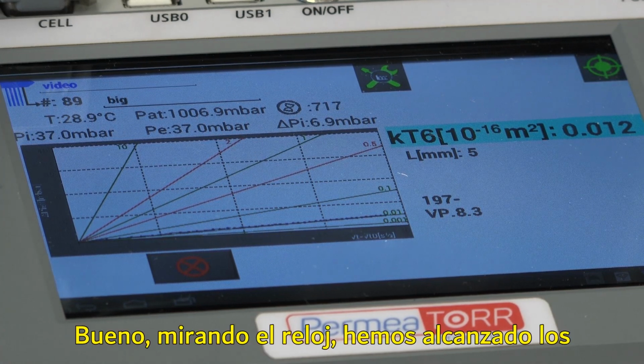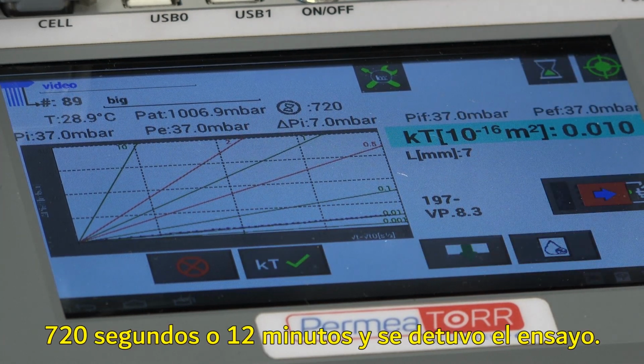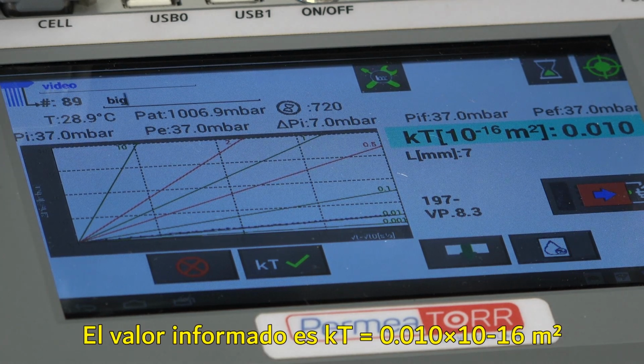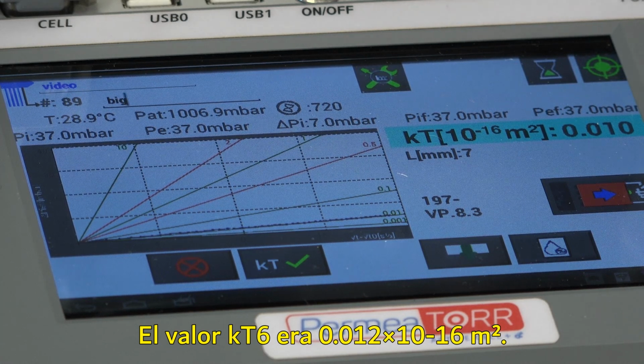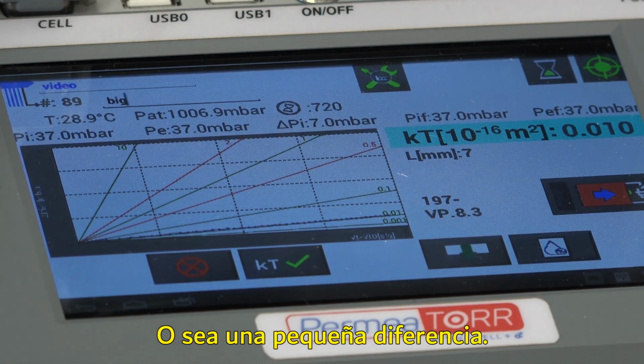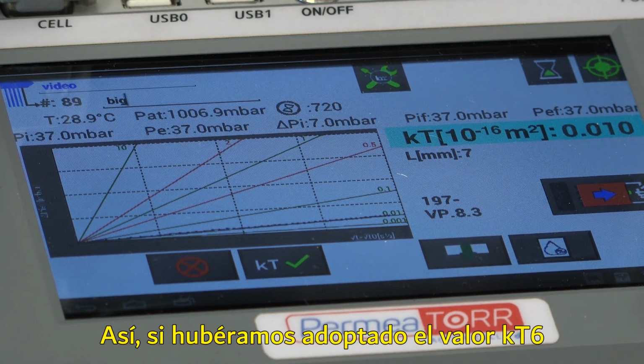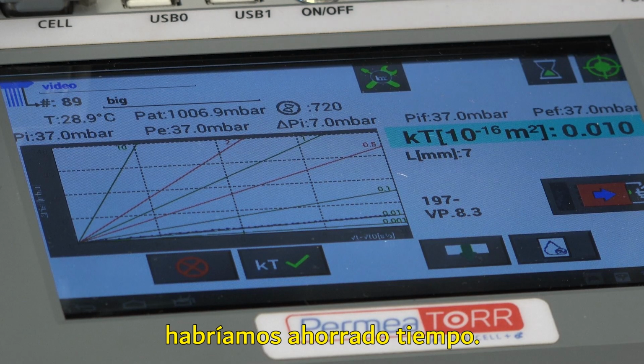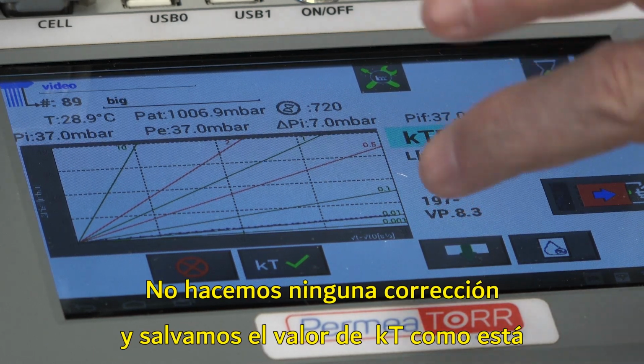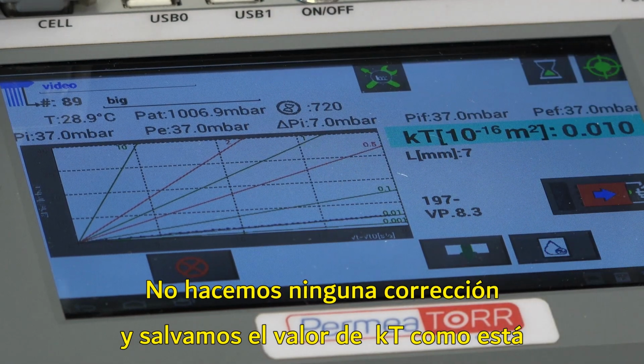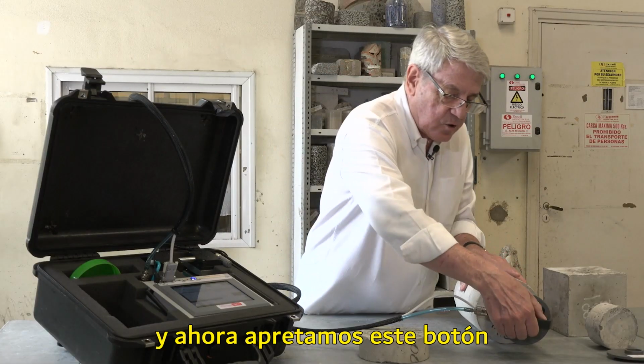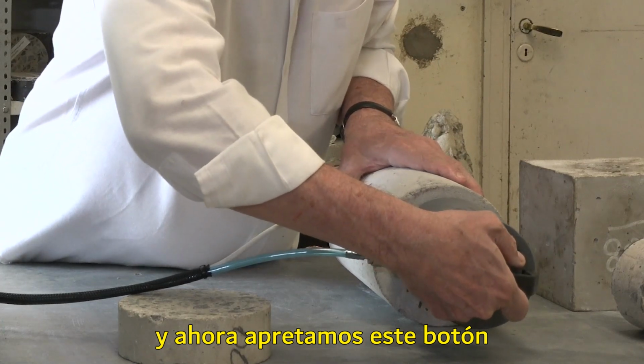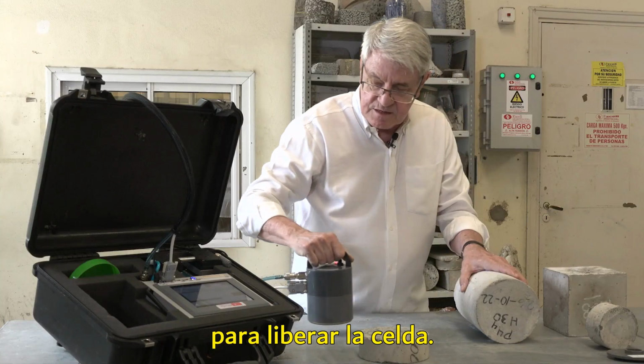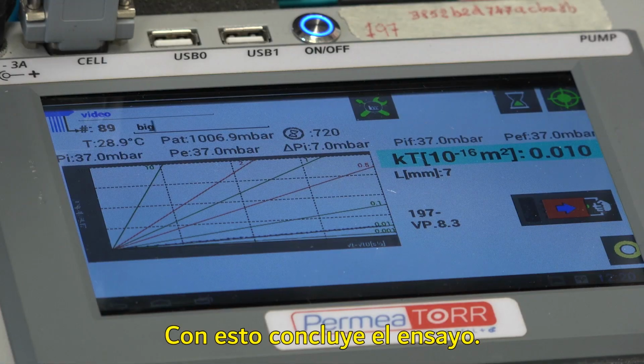Well, now, if you see in the clock, we have reached the 720 seconds or 12 minutes. The test is stopped, and now the value reported is 0.010. The KT6 was 0.012, so you see the difference is very small. So we would have saved time if we had adopted the KT6 value. So we made no correction here, and then we save the value as it is, and now we press the button here to release the cell. And with this, the test is finished.